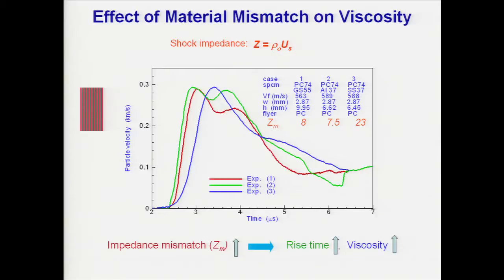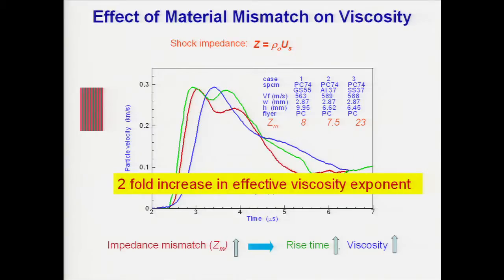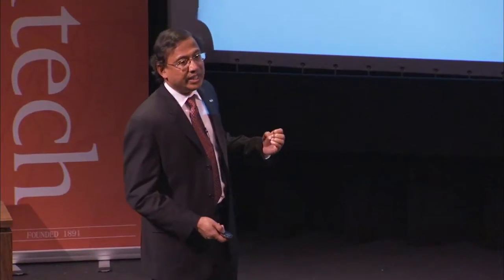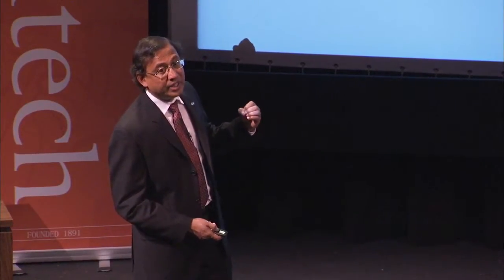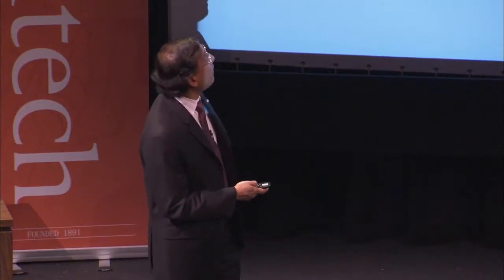so you can dissipate more energy. So the idea in creating this kind of layered armor or bulletproof glass would be to increase this mismatch. At the same time, because the rise time is getting longer, we are increasing the viscosity, with a twofold increase in the effective viscosity exponent. So we can dissipate energy quite effectively using this sort of strategy.